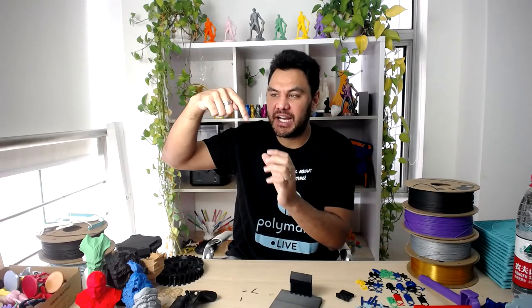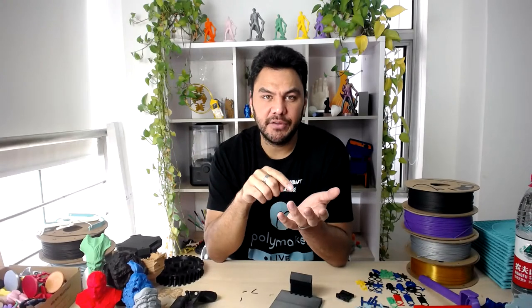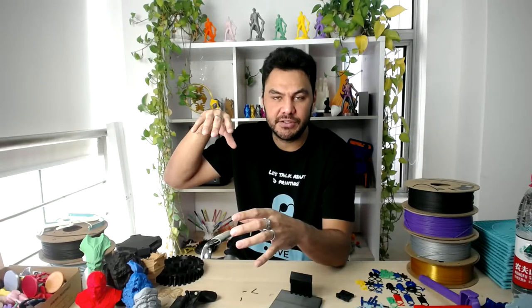But if you retract, as the viscosity is very high all the way to almost the end, then you have a very good retraction. Retraction is what? Retraction is removing the pressure from the nozzle, and that basically works very well. If you check, usually you do retraction because of oozing. Oozing comes from two main things, three if you count the time, but it comes from the residual pressure that is in your nozzle. So you need to bring this residual pressure to zero, and you do that by retracting the filament. And then the pressure inside the nozzle will be zero. So that's one factor that would make it ooze, if there is some residual pressure.